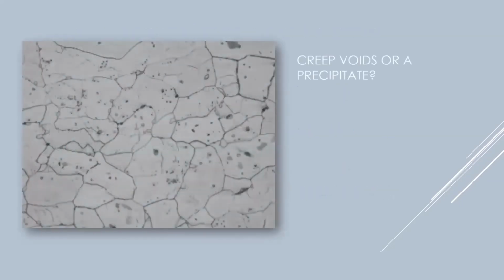So when we look back on this one here, once again, you might say carbides go to the grain boundary also. So when I'm looking at those things, am I looking at a creep void, or am I looking at a carbide at the grain boundary? You have to be able to determine that. And the only way to do that is you raise and lower your stage on the microscope, at rather high magnifications, maybe 600 or 800 times magnification, and you look for what comes into focus first.